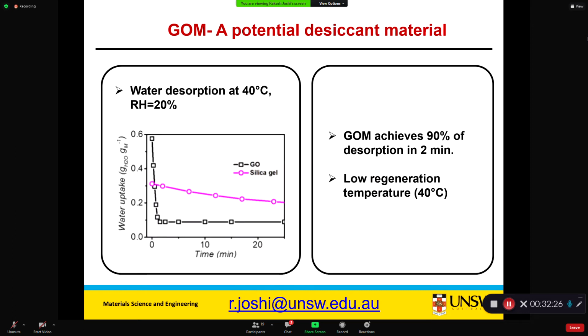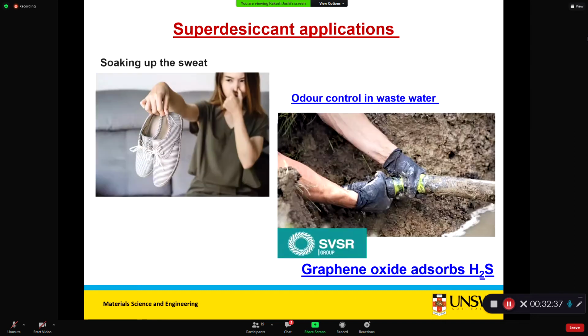And one good thing about it is that it regenerates at around 40 degrees. So this shows that it can be used for athletic wear, and we are working in that direction also. For these applications, we're planning to incorporate graphene oxide in soles and in the clothes, so that it will absorb the moisture.